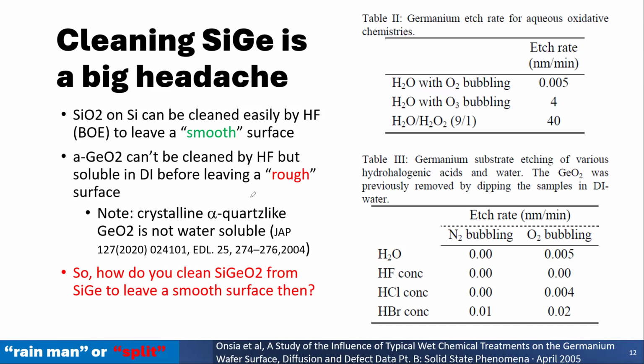But germanium oxide cannot be cleaned by HF. You can clean it by dipping the sample in DI water. All right. And with a little bit of oxygen, with hydrogen peroxide, you can etch quite reasonably well. But that leaves a rough surface. That's nasty, right? You want to have a clean, smooth surface. So before you do a high K, that's the minimum you need to have.